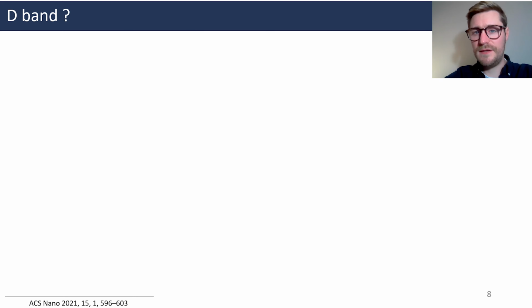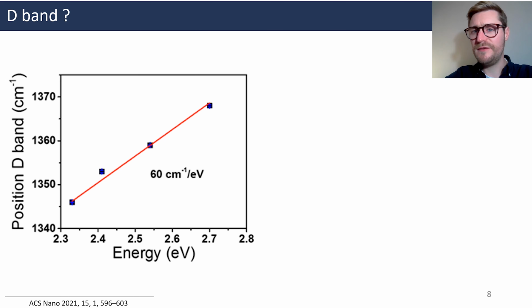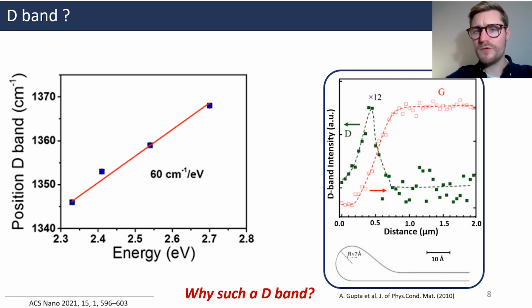What I mean is that this band is coming from the same physics as the classical D-band in graphenic material. Indeed, the band we measured is dispersive. This validates its origin from an iTO branch near the K point. The question then is, why such a D-band? Among the abundant literature on the subject, we found one paper from Eklund's group showing experimentally that the presence of a fold on a graphene sheet can activate a D-band.